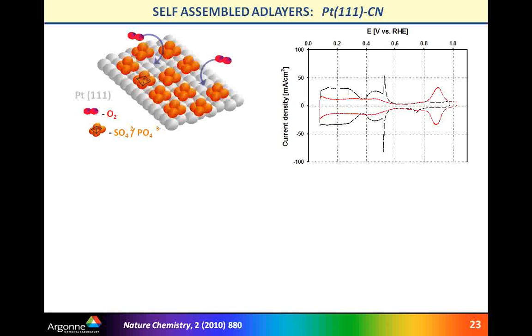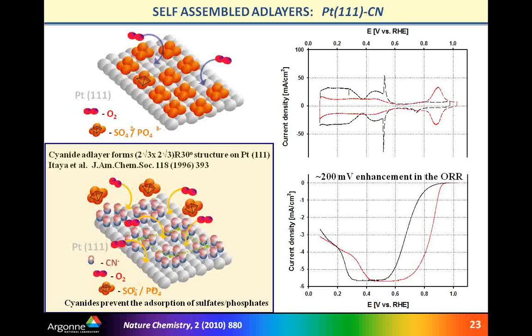Now the voltammetry is basically on, and in this particular case, what we try somehow to protect absorption of these anions, which are blocking the availability of platinum sites, by cyanide. This is a method what Itaya introduced in the 1990s. And in this particular case, what you can see right now, we managed somehow to make very nice structure of cyanide on platinum 111, and this cyanide distribution of the surface is such that allow small oxygen to go through,